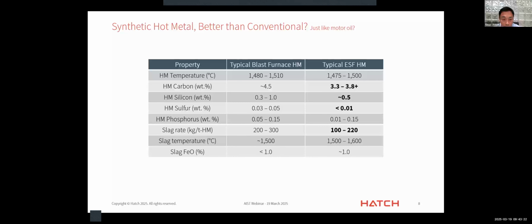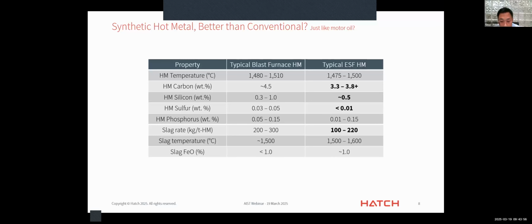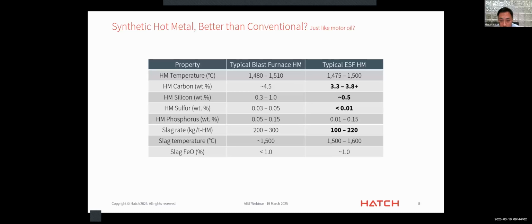So here's a quick summary of what we think a typical ESF hot metal is compared to typical blast furnace hot metal. So synthetic hot metal is better than conventional hot metal, just like synthetic motor oil is. Certainly there are differences, so I'll echo Gerald's presentation. Hot metal carbon is probably the most obvious difference. It's not going to be saturated like blast furnace hot metal, 4.5%, but certainly in the high threes and even low fours is achievable and demonstrated. Silicon level on average is comparable to that from the blast furnace, but we expect it to be a much more consistent level of silicon. Again, that provides significant operational benefits compared to traditional blast furnace operation.